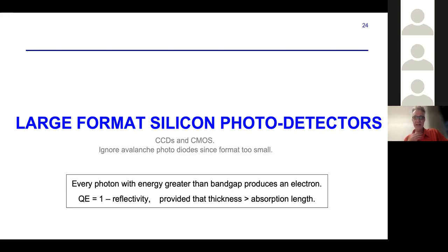So the big deal with the silicon sensor is, as I mentioned earlier, that the QE is basically 1 minus reflectivity. So if you can do really good coatings, you can get really good quantum efficiency. The proviso here is that the CCD has to be thicker than the absorption length of a photon. Now, the absorption length in the ultraviolet is extremely short, so that's in fact a very easy requirement to satisfy, less so at the red end of the optical bands, but we're not worried about that today.